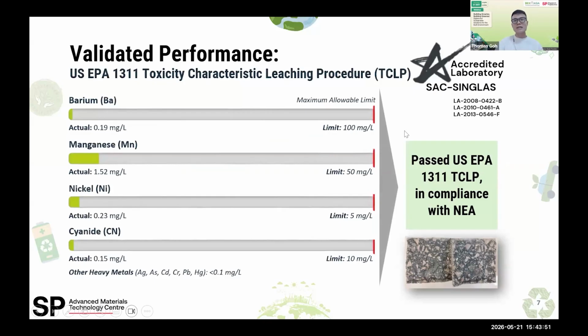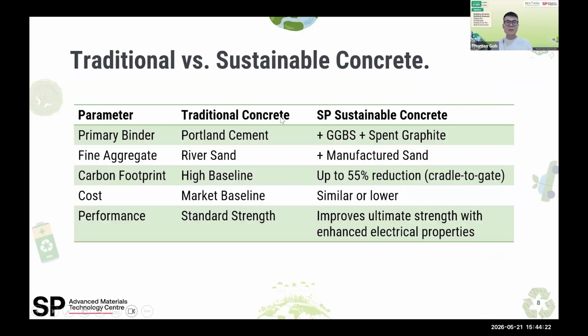Then we also send our concrete to a third-party accredited laboratory to measure the toxicity test in compliance with the NEA standards, which is the US EPA 1311. So you can see that our concrete actually passed all the performance tests with a very negligible amount of heavy metal. And not shown in this picture, it also passed, for example, the silver, the cadmium, chromium, and also phenolic compounds, cyanide, and also fluoride.